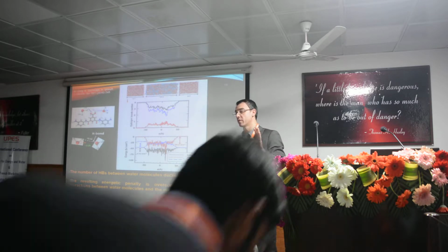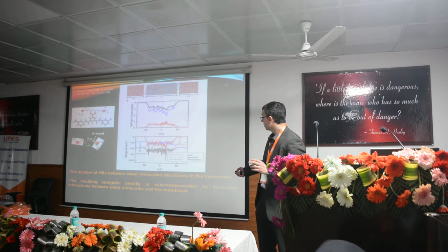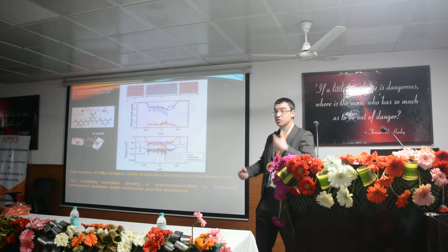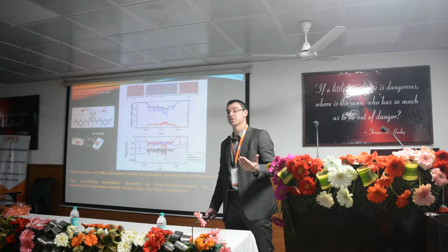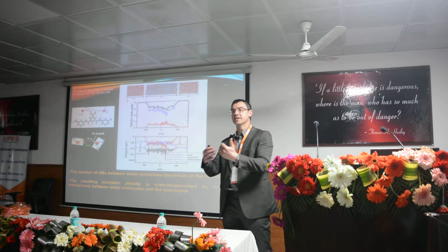This is very, very important because from the thermodynamic point of view, it is a very, very unfavorable condition. And if you compute the interaction energy, if you focus first on the blue line here, it shows you that there is an energetic penalty, rather important, associated with the loss of hydrogen bonds. So, at first sight, water should not enter so easily inside the membrane.